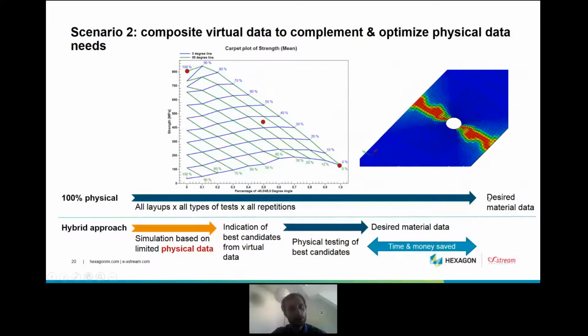And with a hybrid approach where we can start with simulation, what happens is the following. You first perform simulation based on a very limited set of physical data, like laminate information. This gives you an indication of the best candidates from the virtual data results. And from the good candidates that have been identified, it then becomes possible to perform physical testing only for those ones. That means that the blue arrow that you see here, which represents the time and effort needed for testing, becomes really reduced, because instead of testing all possibilities, you test only the right candidates that were suggested by simulation. And obviously the gap between both is the time and money which is saved.